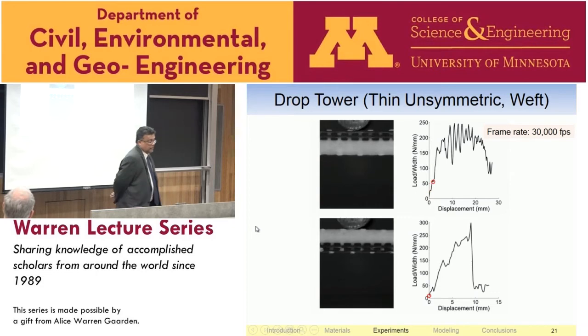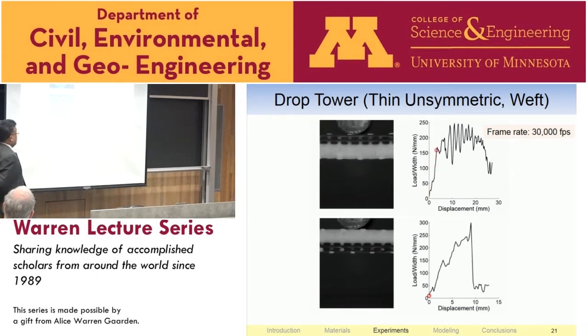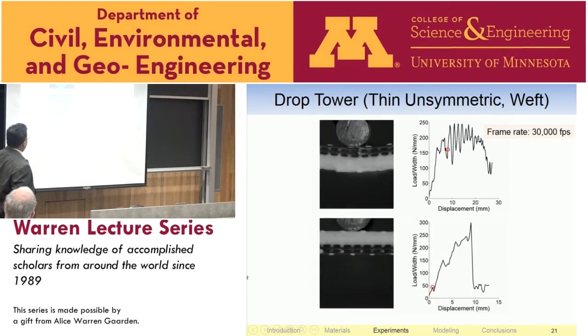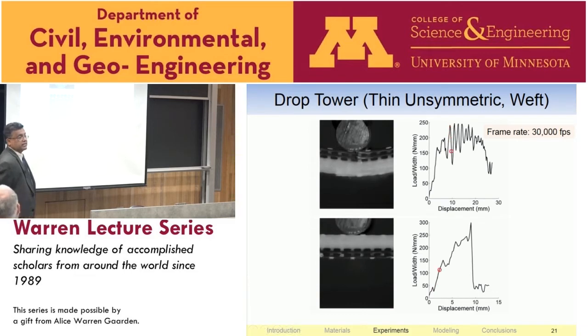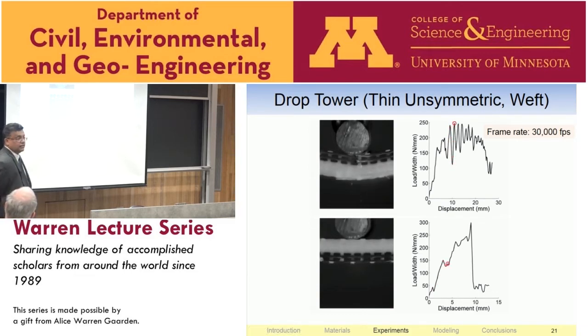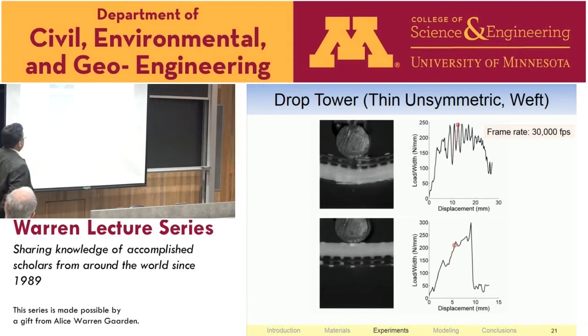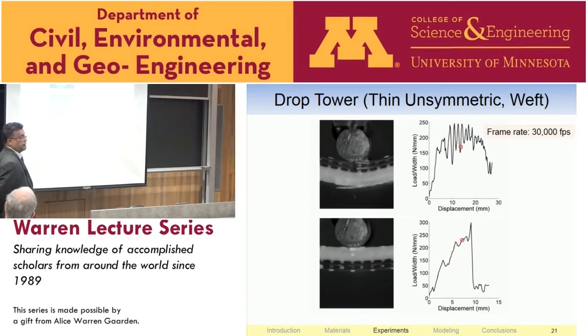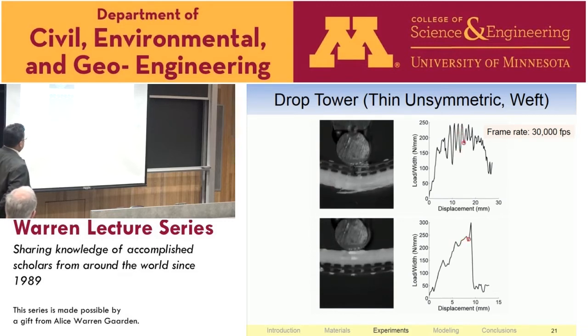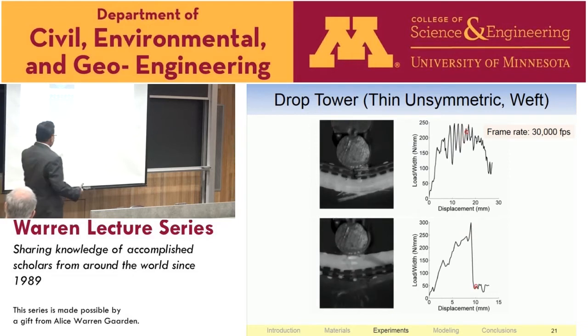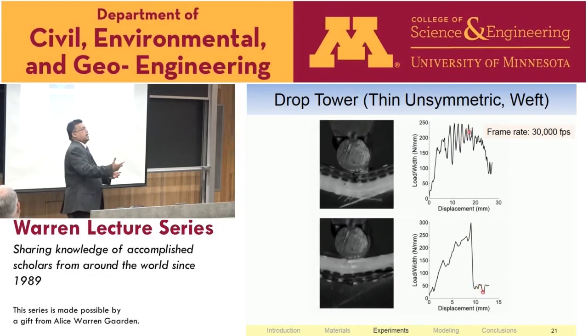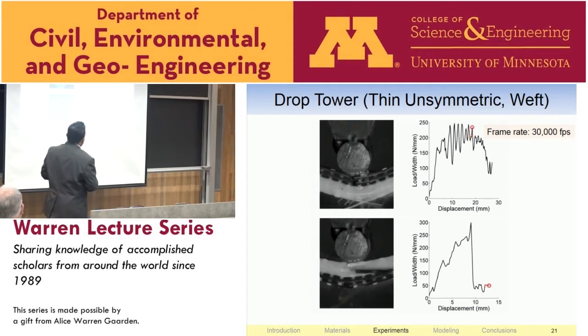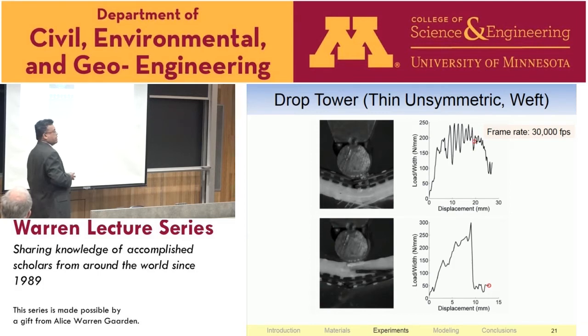It's playing. Good. So you'll see that these oscillations, after you take out the high frequency noise, are failure. There it is. You can see the failure occurring. And each failure point is an abrupt drop because of the localized failure, but the load picks up. So this is not noise. This is actually a deterministic event which is controlled by the microstructure and the fact that it's contained. And you can see the glass. So if you design it well, you can make this progressive failure event last even longer, right? That ability exists for you to control what you do with the material, right? So materials design, controlling structural response.